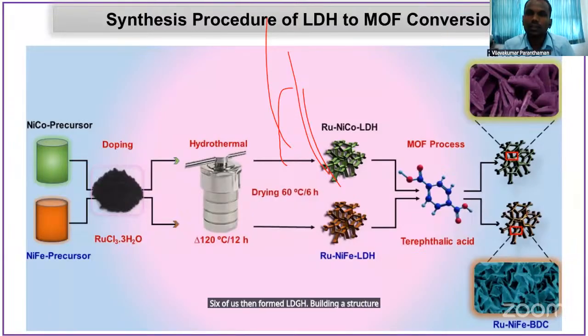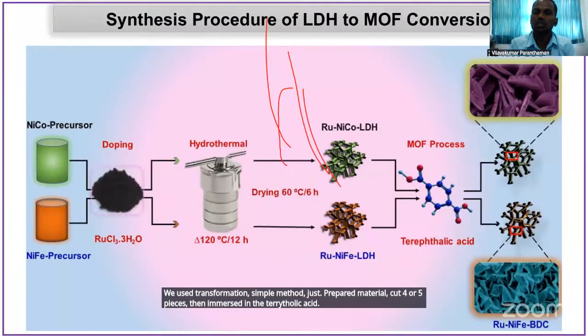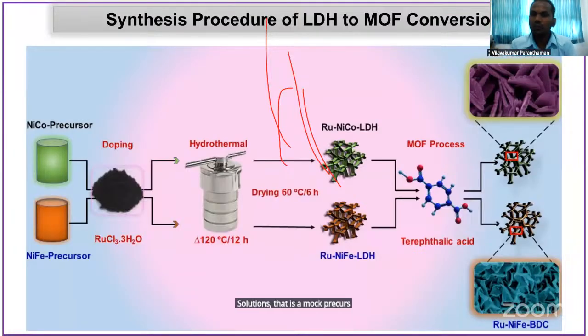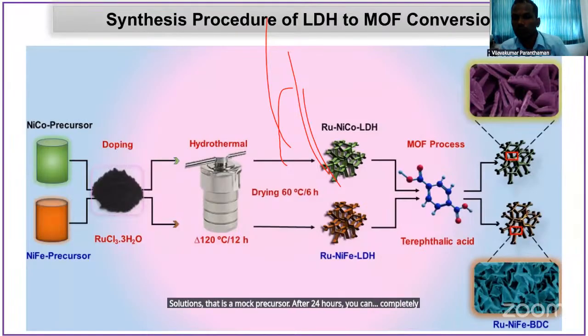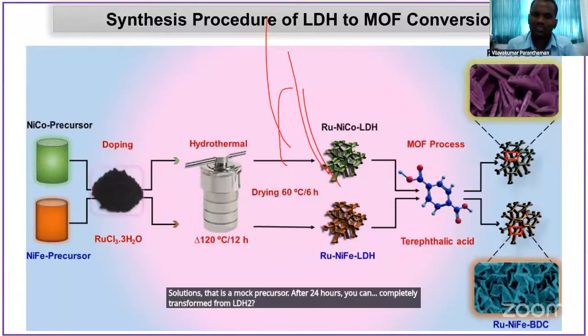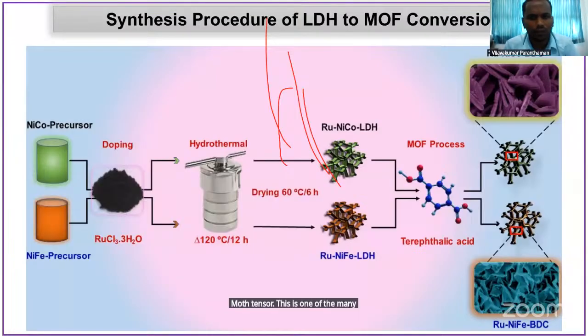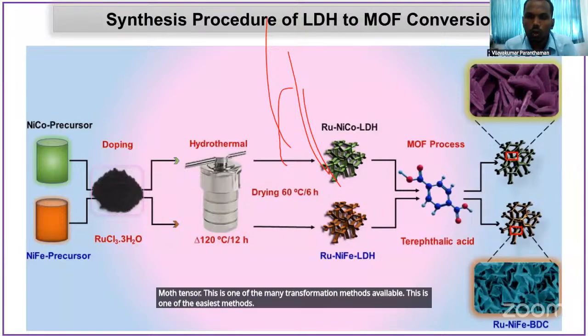Then after drying, we used a simple transformation method: the prepared material is cut into 4 or 5 pieces, then immersed in the terephthalic acid solution, which is the MOF precursor. After 24 hours, it is completely transformed from LDH to MOF. This is one of the many transformation methods available, and one of the easiest methods to transform LDH to MOF.